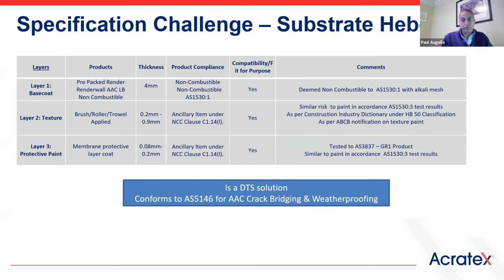If we now take it into what a specification primarily looks like by substrate, let's look at Hebel AAC, for example, stepped over a 3-layer system. Layer 1 is the base coat material, which is generally what we call a pre-packed render. In this area, we've had a product tested that complies to 1530 part 1, which incorporates the mesh, because one of the requirements for AAC is that you need a reinforced alkaline mesh within to cover your joints and take movement over the joints. So that first layer, render and mesh combined together, complies to 1530 part 1.